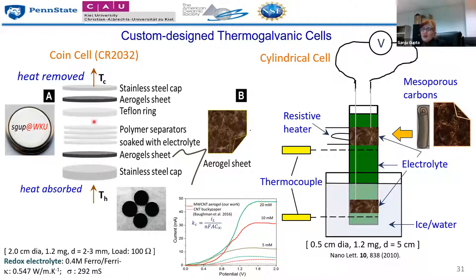So you see here two different configurations. One is the classic coin cell, the button cells that we can buy again from the shops, for instance, where we replace our electrodes. So we use either a symmetric configuration, meaning both the cathode and anode are the same material, or even an asymmetric one, meaning two different materials. We didn't try all the combinations, of course, because it was a lot of work, but we used a couple of them and we observed that the asymmetric has a slightly better performance than the symmetric, interestingly enough.